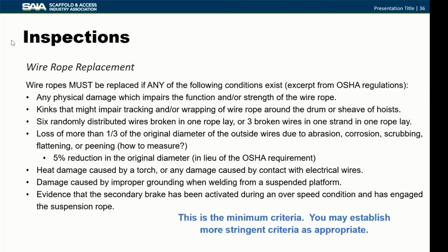Any heat damage on the wire rope is definitely a cause for taking that rope out of service. Any damage caused by improper grounding when you're welding, again, that is an automatic that the rope needs to be taken out of service. And then any evidence that the secondary brake on a traction hoist has activated during an actual overspeed condition and it's engaged on the wire rope, that is another instance when the rope should be taken out of service.